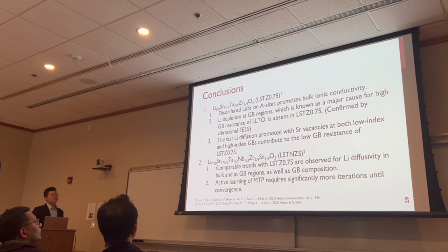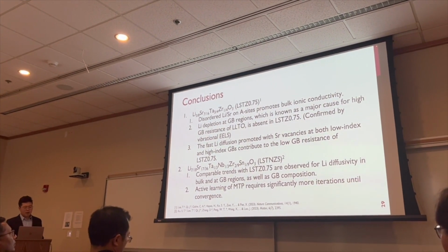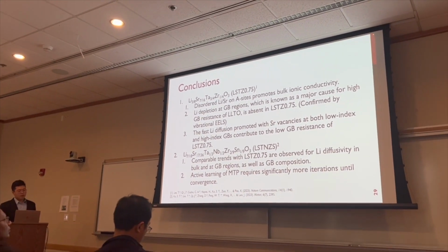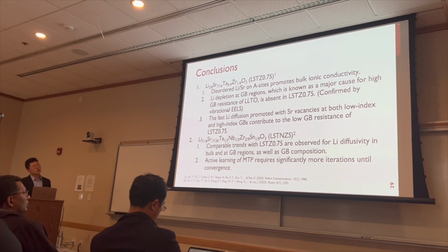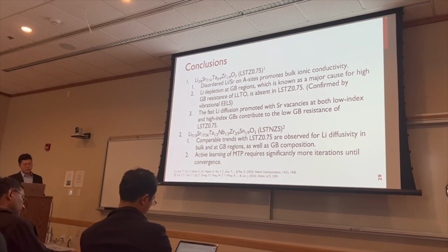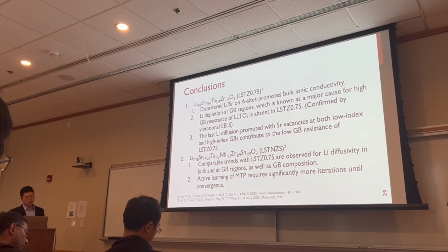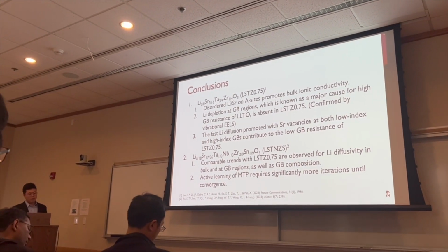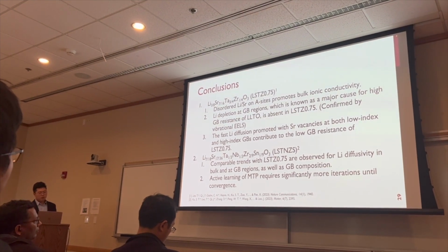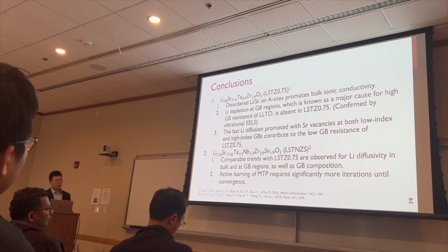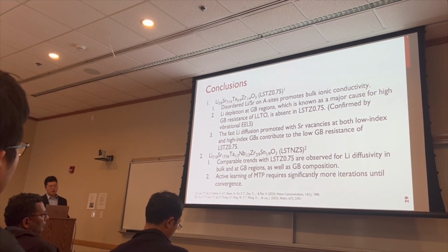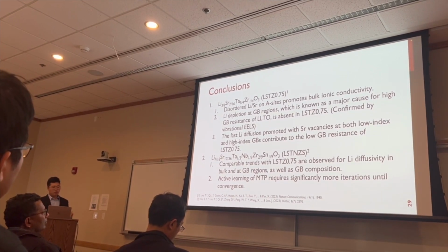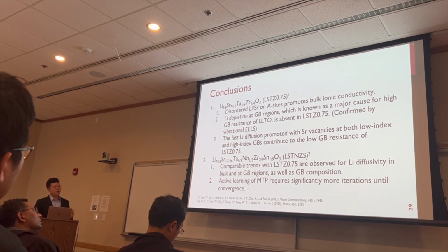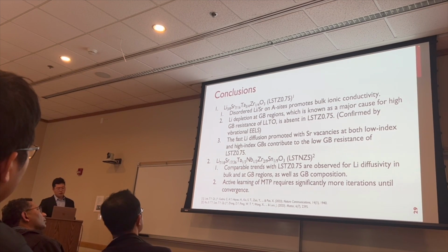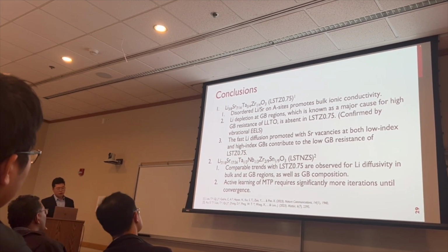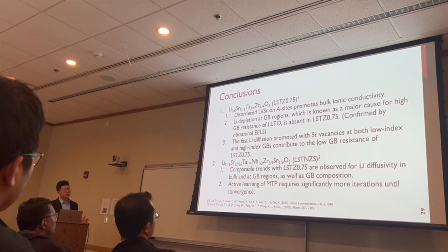And to give a conclusion of this study, for these 2 materials, LSTNZS and LSTZ 0.75, we found that the disordered lithium strontium on A site promotes the bulk ionic conductivity, and lithium depletion at grain boundary, known as the major cause for high grain boundary resistance for LLTO, we didn't observe in the LSTZ system. And the fast lithium ion diffusion is promoted with the strontium vacancy at both the low index and high index grain boundaries, which overall together contribute to the low grain boundary resistance of this LSTZ family of material. And especially for this LSTNZS system, I want to highlight again, active learning of MTP requires significantly more iterations until we reach convergence.